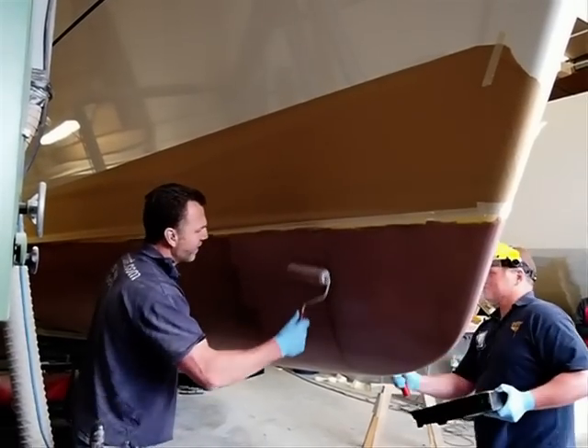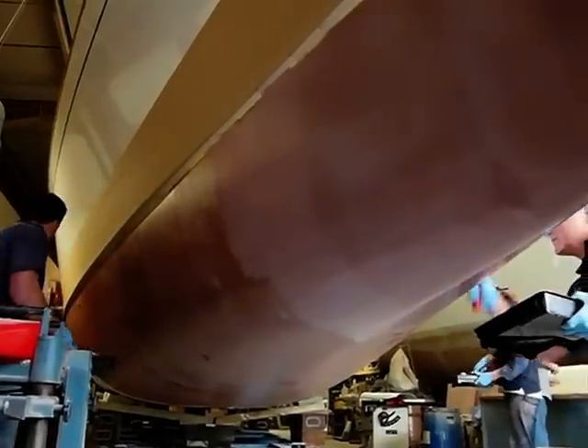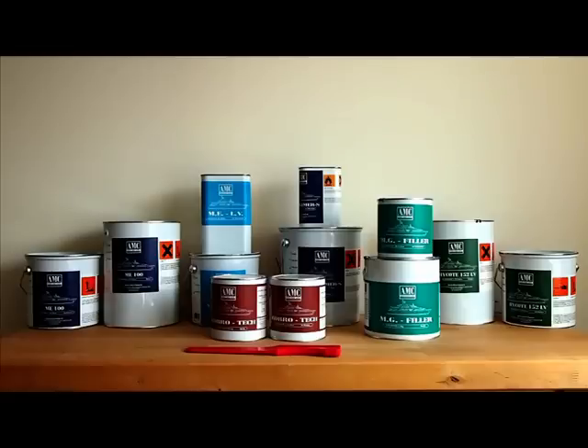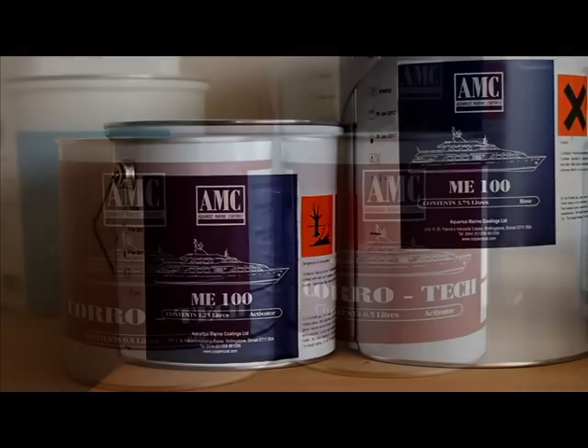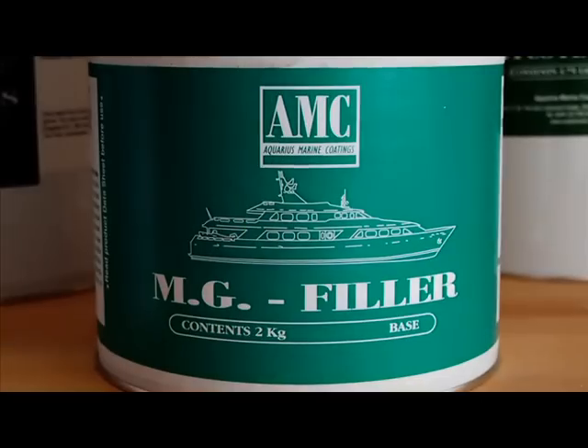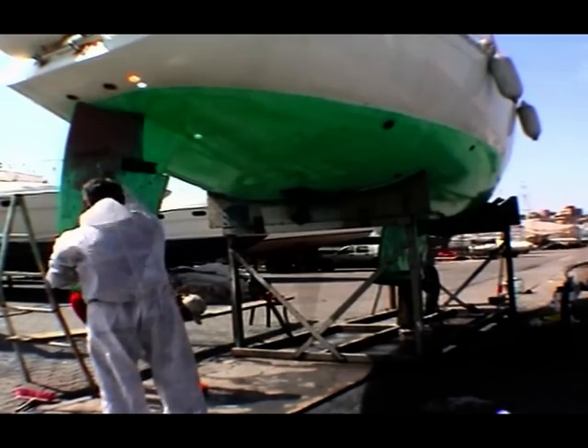You've just seen the application of Coppercoat to a cleaned and abraded fiberglass hull. However, for those requiring a greater level of protection against osmosis, Coppercoat can also be supplied with AMC's own range of matching epoxy resins. By applying additional resin before the Coppercoat, a thick and highly impermeable barrier can be created. Furthermore, Coppercoat can be applied over most proprietary brands of marine epoxy primers and anti-osmosis systems. Though please do check the compatibility with AMC or your local Coppercoat distributor.